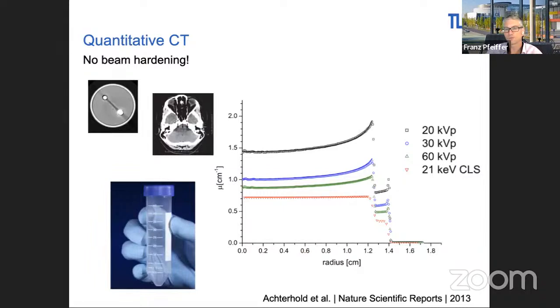Beam hardening occurs because you're using a broad spectrum. What that basically means is that if you don't do anything against it, like applying algorithms or putting in a monochromator, you always have cupping artifacts and streaking artifacts, which are not nice. If you're particularly after doing quantitative work on densities and 3D distributions, a monochromatic source will always be better in terms of giving you more detailed information on distributions of various densities in a sample.